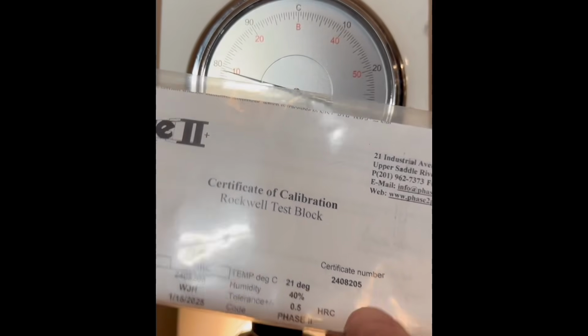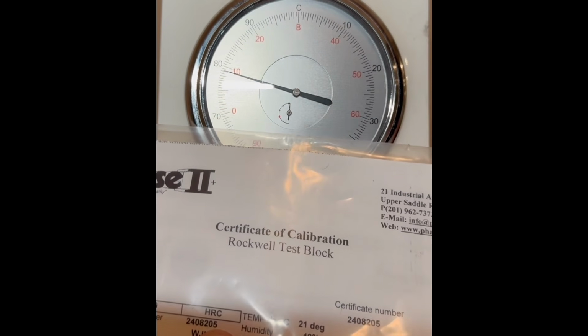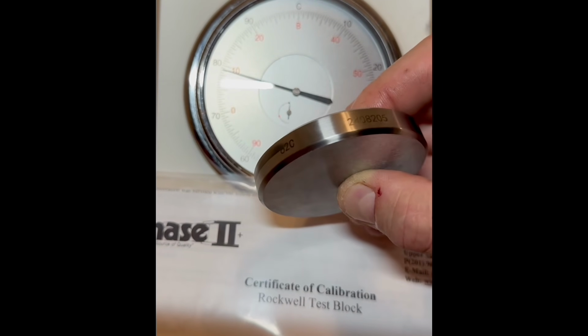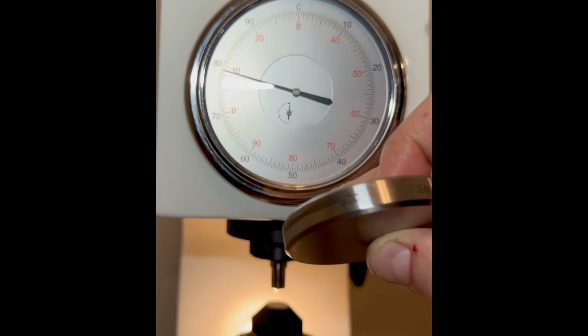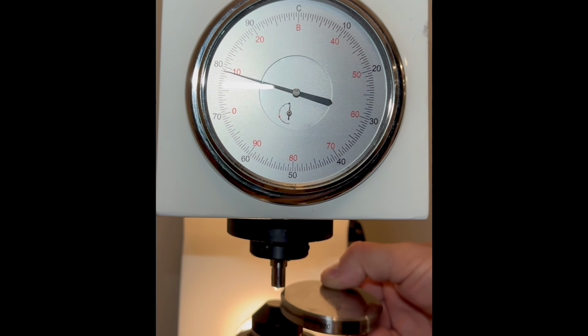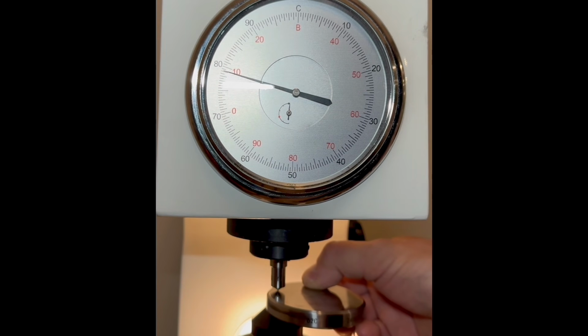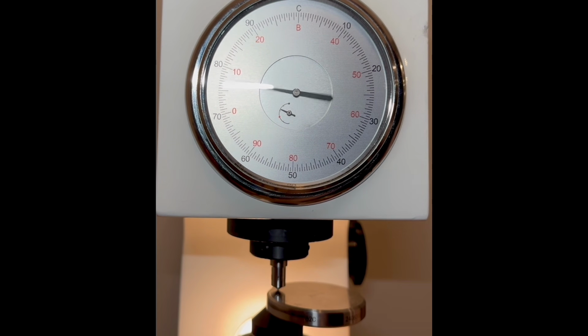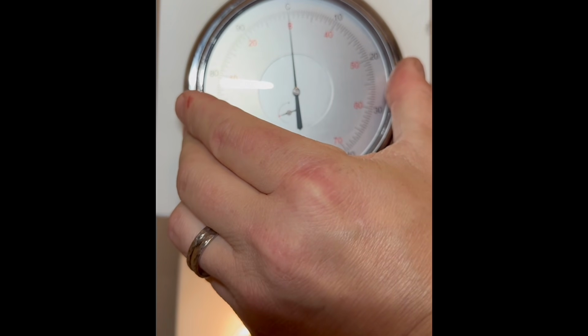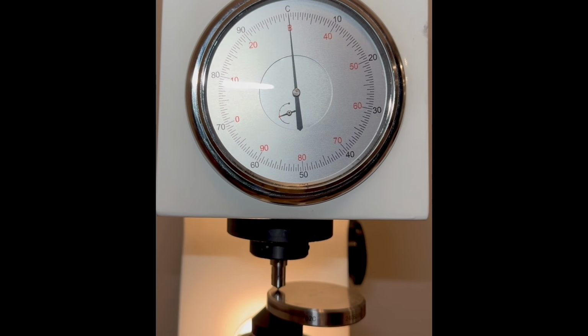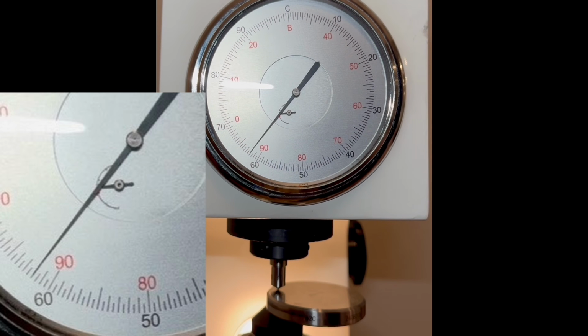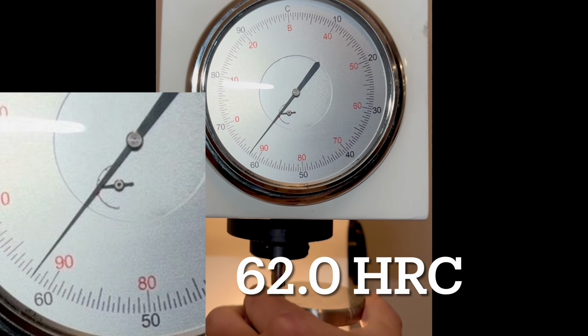As usual, I start all my hardness tests with verifying the calibration of my Rockwell tester. I use an NIST independently certified calibration block that is rated, as you just saw from the paperwork, to be at 62 HRC. This segment is accelerated 2x because each of these tests takes a little over 30 seconds. Now I'm waiting for the major load to drop, and the result is 62, spot on as calibrated.